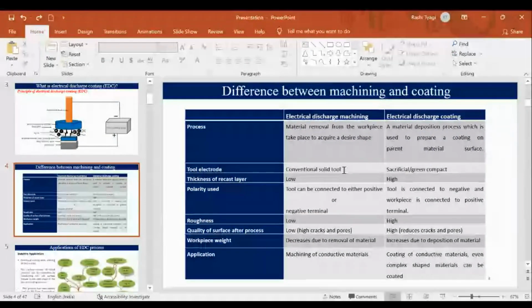Then the tool electrode. In EDM, as I have already told, we use a conventional solid tool. And in electrical discharge coating, we use a sacrificial tool, or you can say green compact tool, which means it will give the material. It will give the material. That's why it is called sacrificial.